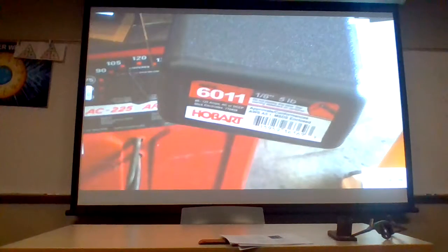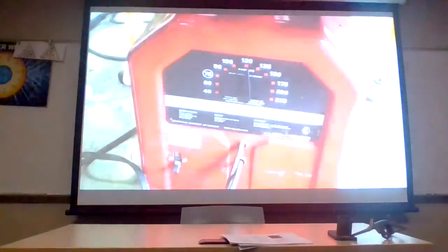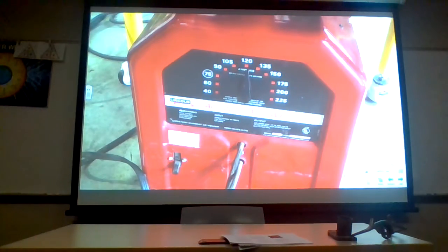Even with a little buzz box like this, it goes down to 40 amps. You can see, up to 225, down as well as 40. Turn it down to about 40 amps, you can weld, actually wouldn't be in trouble welding even 18 gauge. This is 16 gauge hot rolled steel here, outside corner joint. And then the 6011 is really good for a little downhill weld like this. You can do fabrication on like square tubing. It's not quite as easy as using MIG, but it's like the next best thing.